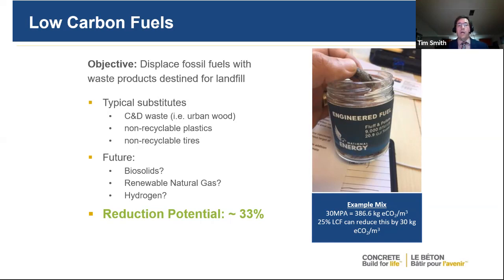So if you take an example of a 25% reduction by using the low carbon fuels, we can reduce the 30 MPa mix that I mentioned earlier, from 386, by 30 kgs per cubic meter. So there's a substantial amount of savings that can be achieved by burning different types of material in our kilns.